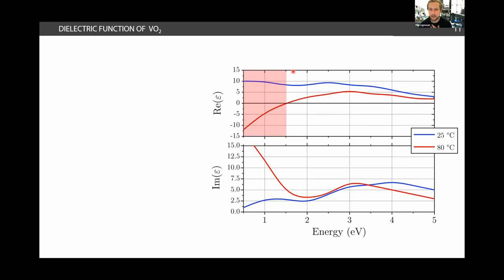Here is just another visualization of the metal to insulator or insulator to metal transition. This is dielectric function or permittivity if you wish, real part and imaginary part, and whenever your real part of permittivity goes below zero approximately you can say that the material behaves like a metal and here you can see two temperatures. So this is our measurement using spectroscopic ellipsometry. We extracted dielectric function of our thin layer of VO2 and you can see how in the visible and near IR region VO2 nicely shifts from high index dielectric with of course some losses into metal behavior.